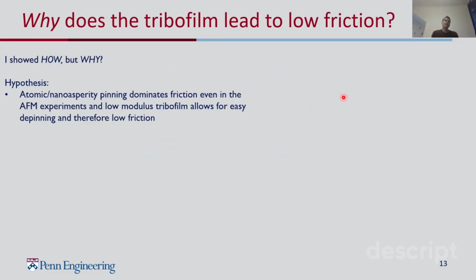So I've already showed that adhesion and shear strength change a lot, and that's how the tribofilm provides low friction. But we're also interested in why does the tribofilm provide low friction? And we don't have a bulletproof answer for this, but we do have a hypothesis that's consistent with our data. Our hypothesis is that in the nanoscale sliding case, the high friction that we see is dominated by atomic and nanoasperity pinning and not interfacial bonding.